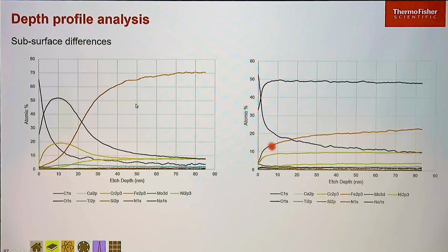So it's not the chrome we see coming up immediately and forming that barrier layer. We see the molybdenum, we see nickel, we see the iron, the chrome. So we're seeing all the major components of the material. And that's what we see over here. Once we get through that passivation layer, we don't see it on this side at all.